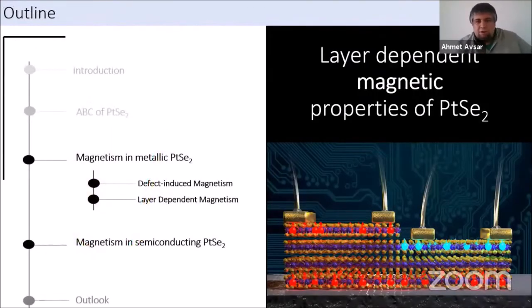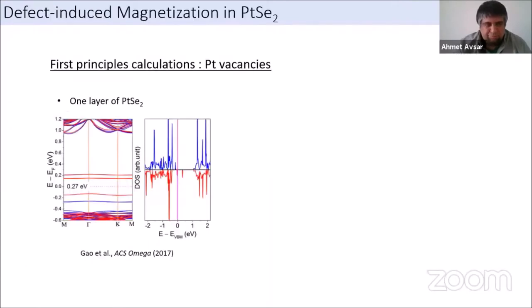So now I will be talking about the platinum diselenide (PtSe2) case for the magnetic response. Indeed, this is the work which brought our attention to this material. A group at IMRE in Singapore had this prediction that if you have a single or double platinum vacancy in this platinum diselenide (PtSe2), the material becomes magnetic. Basically, they predict 6 Bohr magneton per defect for monolayer.